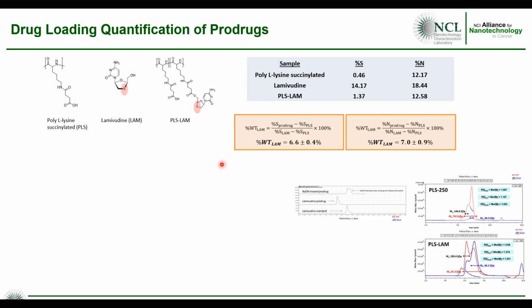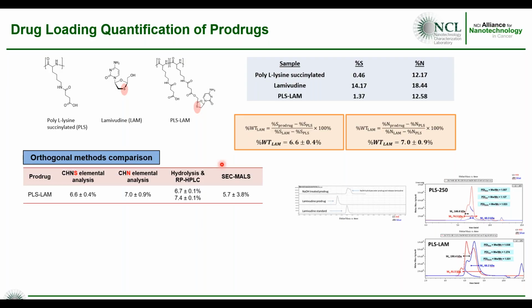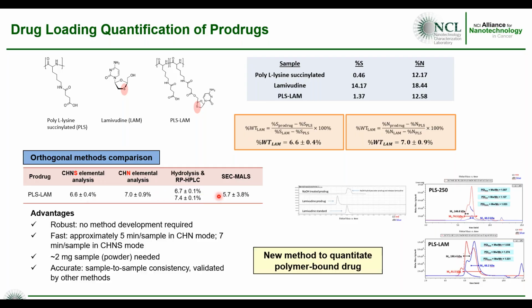So we did that, and we compared this with traditional methods such as hydrolysis and reverse phase HPLC, as well as size exclusion chromatography. And you see we're getting very good results across the board using very different techniques. What's nice about this technique is that it's very easy to do. There's no method development. You simply combust the sample. It's a very fast run, roughly 5 minutes per sample. You need about 2 mg of sample in a powder form for this to work.